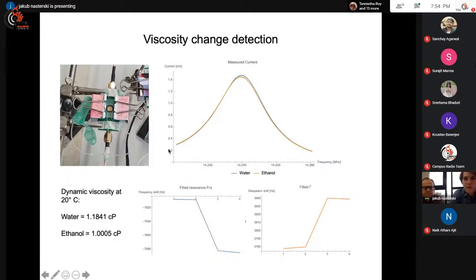The blue is the curve for the water. Orange is ethanol. Because the viscosities are quite similar, as you see here, it's only slightly larger for water. The change is not that visible, but you see that the peak has decreased for ethanol and also moved a little bit to the left. So that's shown here. The resonance frequency fell; those first 2 scans are water, those second 2 scans are ethanol. And the frequency decreased.